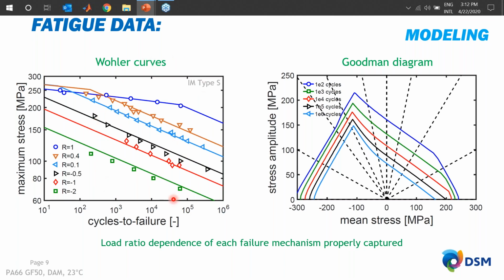But the advantage of having this based on a model is that we now can predict the performance at any arbitrary R value without measuring it. So we can also interpolate and extrapolate and predict the load ratio dependency of each failure mechanism properly. And this is illustrated here on the right with the so-called Goodman diagram, where they plot the mean stress versus the stress amplitude, which allows you to give some direction when you have a variety of R values in your part.